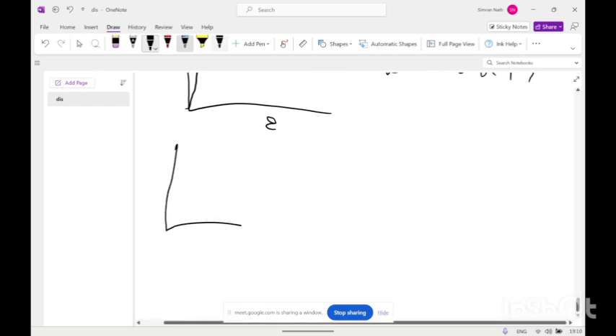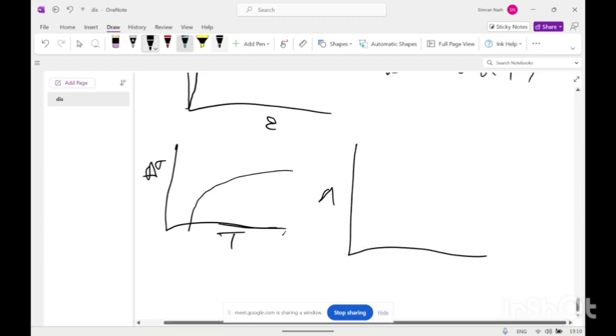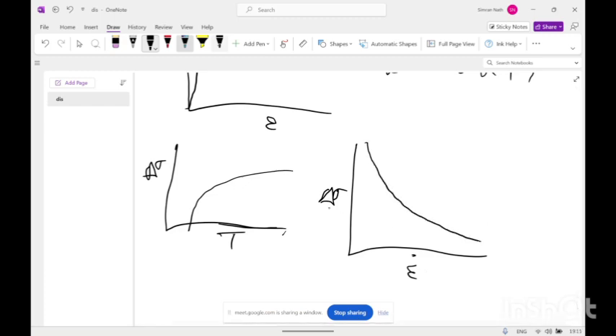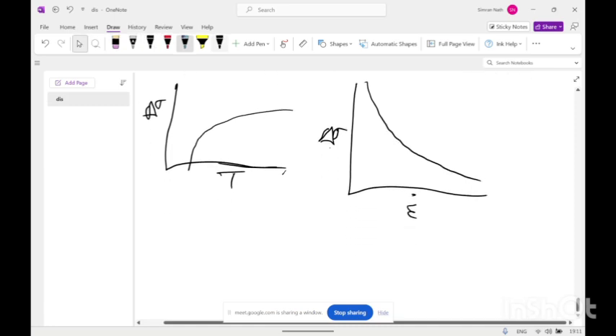If we plot a graph between delta sigma and temperature, there is an increase in the magnitude of the serrated flow. While if we plot a curve between delta sigma, the magnitude of the serrated flow, and the strain rate, there is an inverse proportionality: with increasing strain rate, delta sigma decreases.